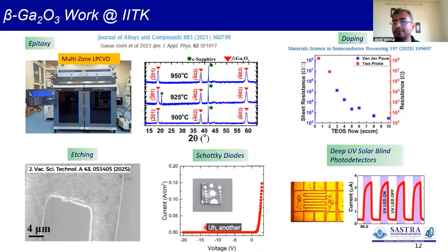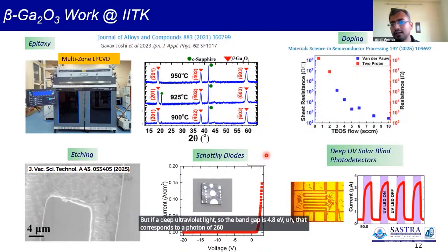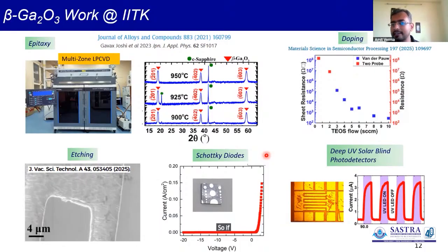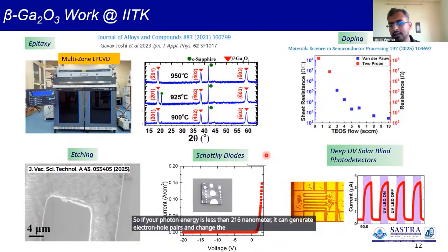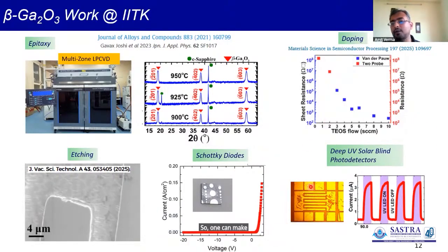Another application of these materials is that because their band gap is very large, when visible light falls on them, they do not generate electron hole pairs. But if it is deep ultraviolet light, with the band gap of 4.8 eV corresponding to a photon of 260 nanometer, then a photon with wavelength shorter than 260 nanometer can generate electron hole pairs and change the resistance of the material. So one can make deep ultraviolet solar blind photodetectors using them.